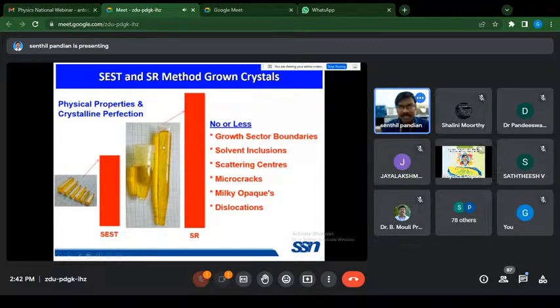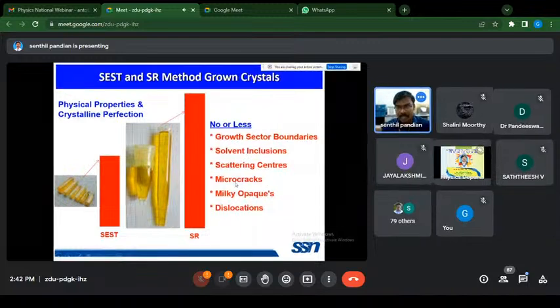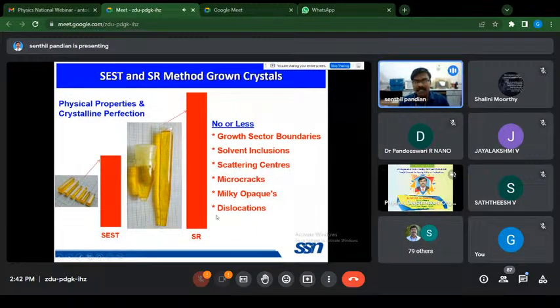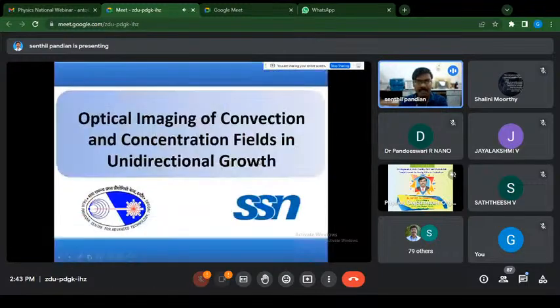But in the case of the SR method, what we have done is we have tried to avoid the grain boundaries in the grown crystal. So we can easily avoid or reduce the grain boundaries, and we have maintained a uniform temperature so that one can avoid solvent inclusion, scattering centers, microcracks, milky opaque regions, and have less dislocation density, which clearly indicates that the physical properties and the crystalline perfection of this SR grown crystal are high, superior compared to the small size conventional method grown crystal.